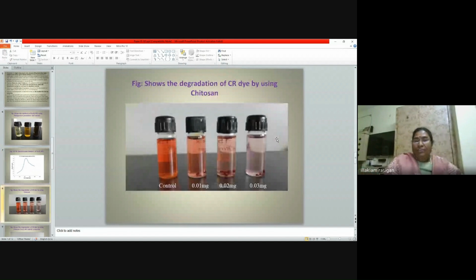Then afterwards, I have coated this nanoparticle with chitosan. I checked whether it has the degradation capacity for Congo red, since it is a prevalent dye present in the textile industry. So I have chosen Congo red. I have prepared various concentrations of nanoparticle, and I have incubated. The removal of color is positively correlated as the concentration increases.